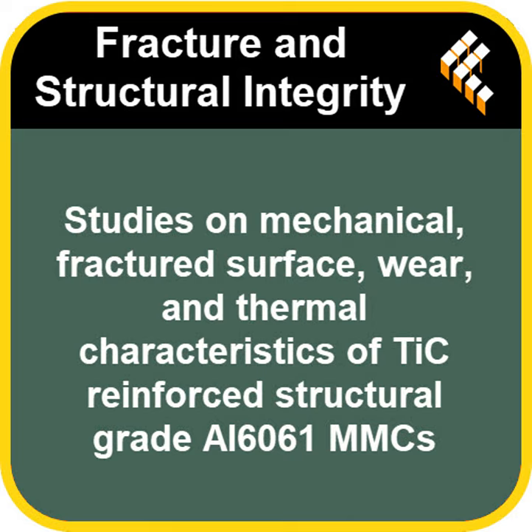Fascinating. What about how the material ultimately breaks? Did adding TiC change the fundamental fracture behavior? It absolutely did. A noticeable shift. The unreinforced Al6061 alloy typically exhibited what's called a dimpled morphology on its fractured surface. Lots of little craters. Dimples. Yeah, it's characteristic of ductile failure. It means the material deforms and stretches considerably before it finally breaks. It gives you some warning.